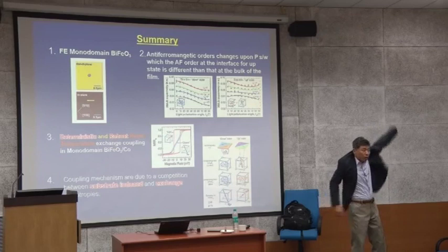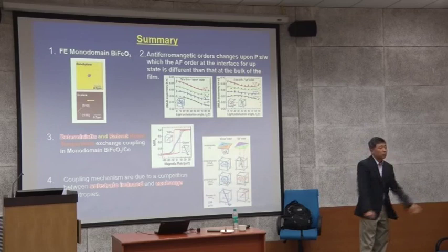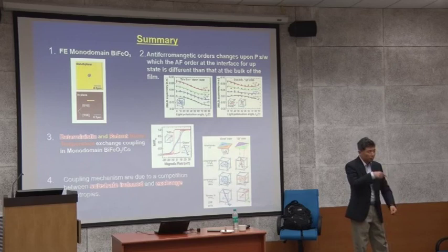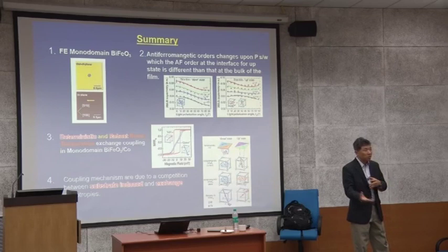So the voltage required depends, as I said, on your coercive field. If the coercive field is high, you need a larger field. And for your PFM measurement, PFM usually comes with its own electronics, usually running 20 volts or less. But if you want to go to higher voltage, you can attach an external power supply. But usually the range is 10 volts or 20 volts or less.